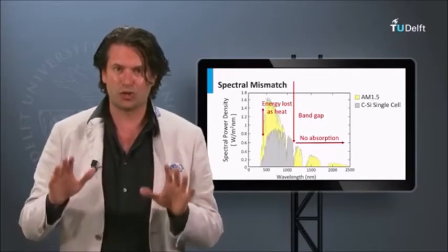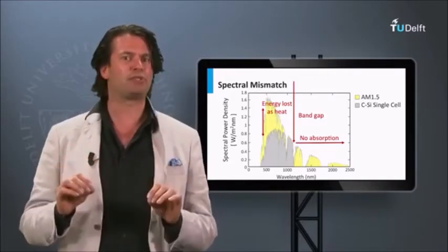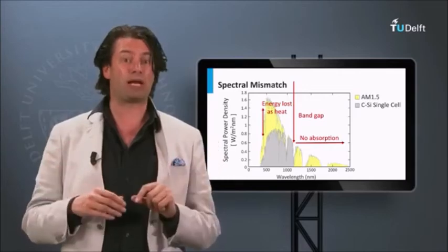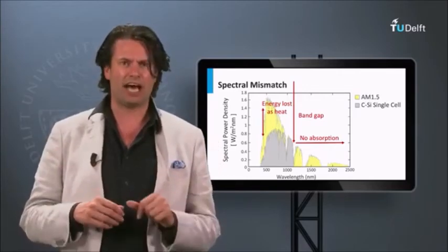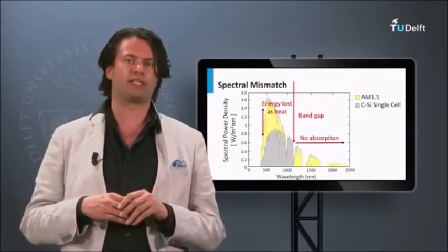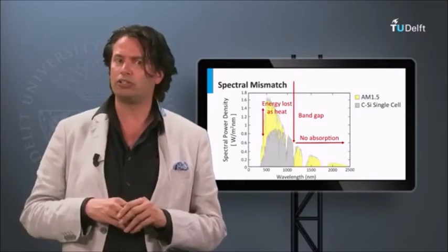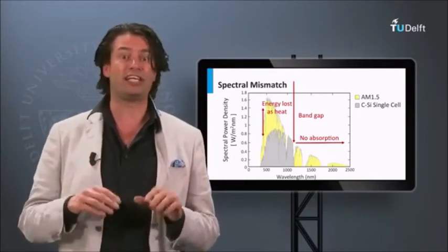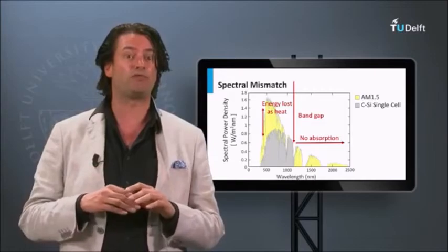First, as the solar cell is at a certain temperature, it will act as a black body radiator itself and emit light in the far infrared. This energy loss is roughly around 7% of the incident energy of the AM1.5 solar spectrum.